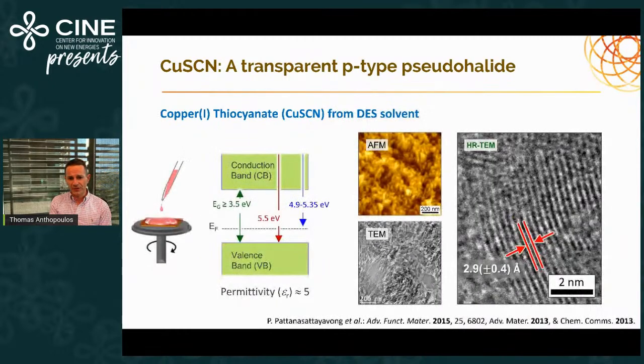So the end result of this material is that it's a wide band gap. It's over 3.5 electron volts, so it's optically transparent. And it's p-type in character. It's actually an intrinsic p-type material. And it's highly polycrystalline when you solution process it from suitable solvents.